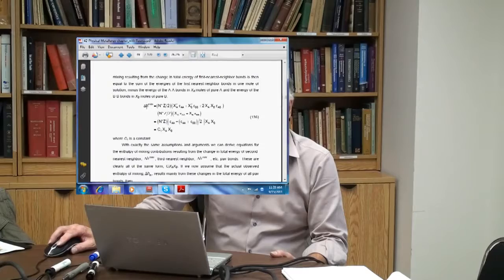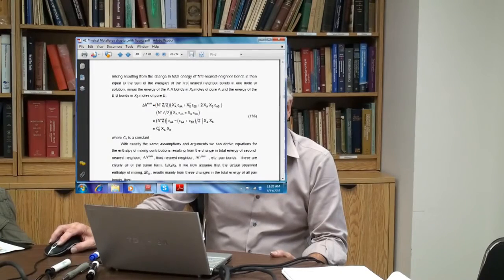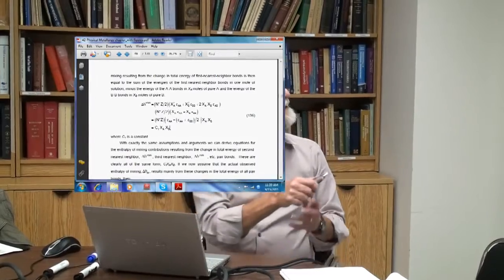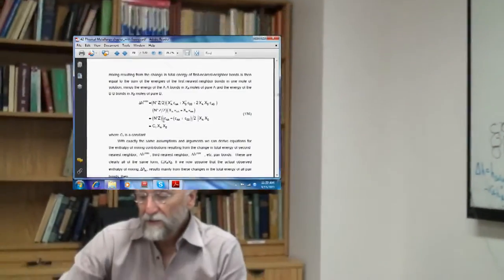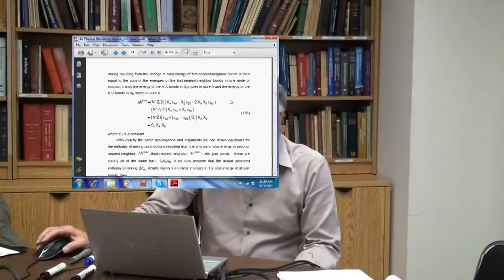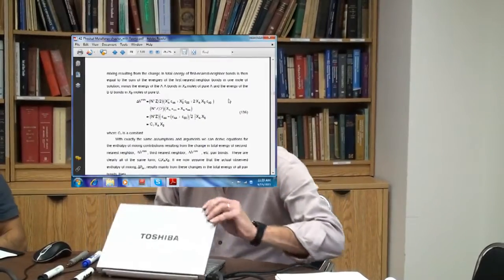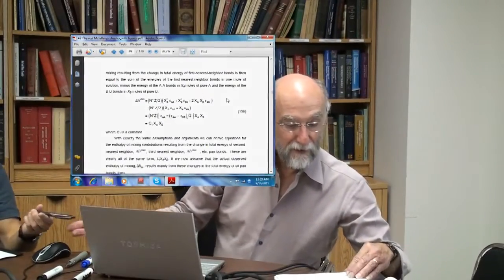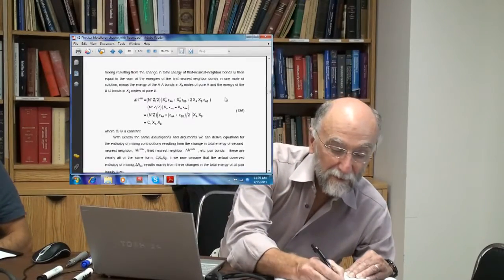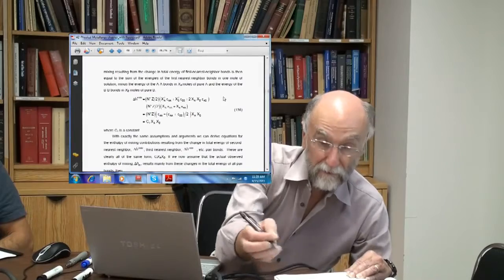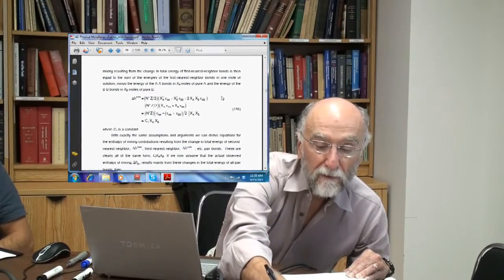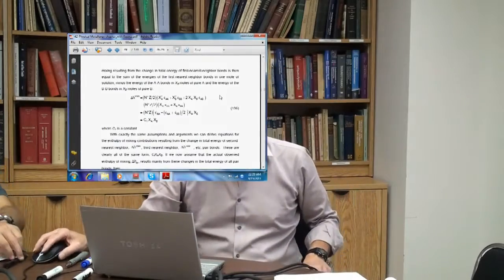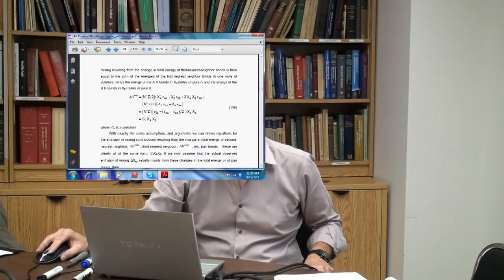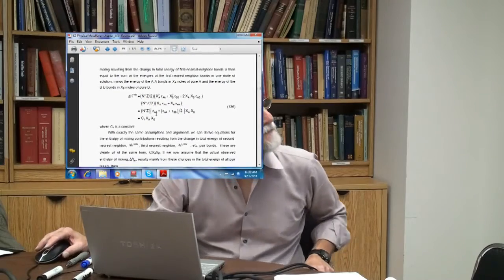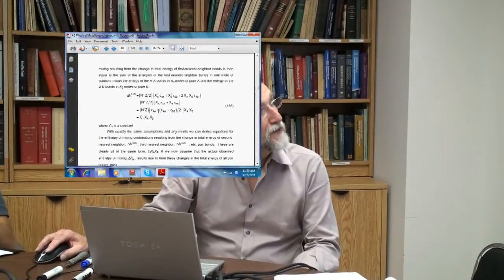And you end up with the enthalpy of the first nearest neighbor terms is a constant times XA XB. So you see we're getting into the XA XB term here now, times a constant. Where the constant is the difference... Jesus, another error. How does this happen? This here clearly should be epsilon AB. Should be epsilon AB, minus epsilon AA plus epsilon BB.